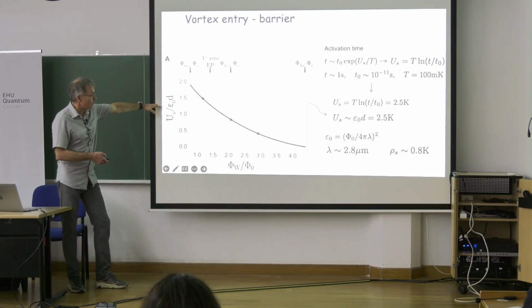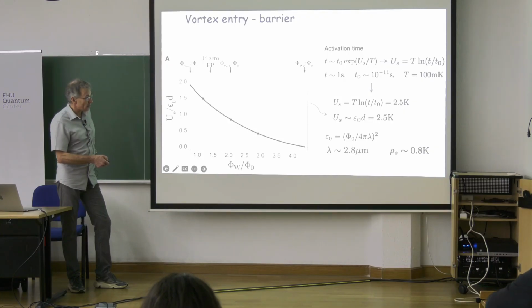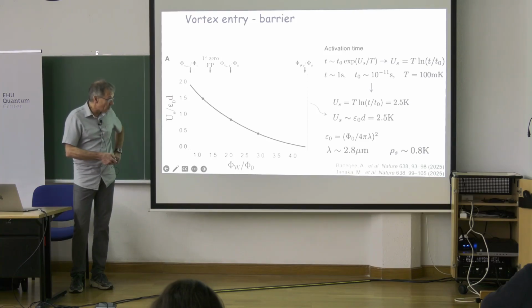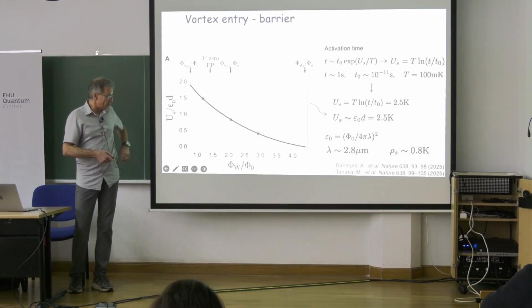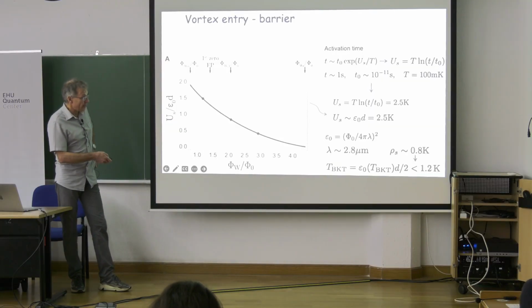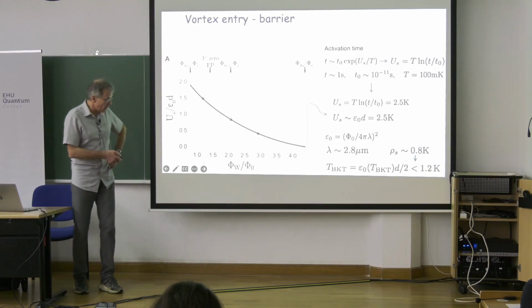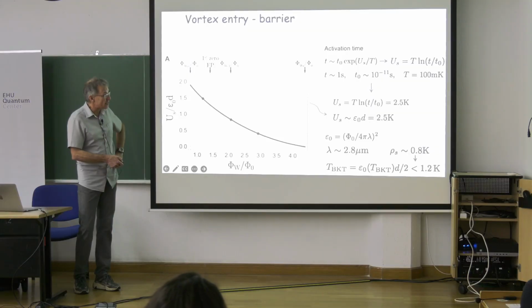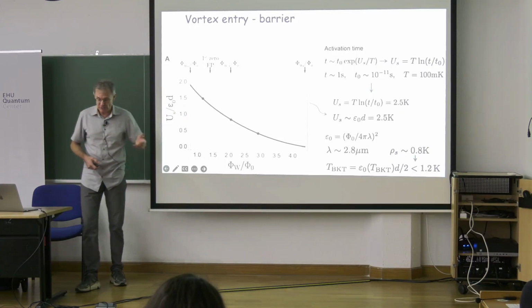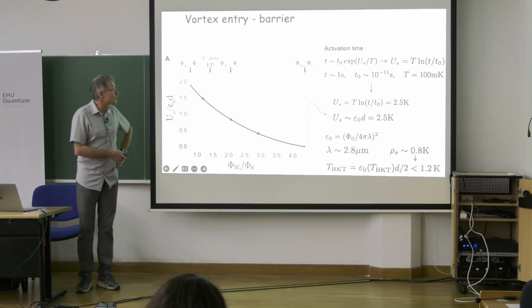From the other side, from this theory, this barrier is about the energy of a vortex in the film, which is the flux quantum divided by the London length squared. So equating this to this, we get a London penetration depth of about 3 microns and a superfluid density of about 1 Kelvin, which agrees well with the recent kinetic inductance study of two leading groups from Harvard and MIT. They study another bilayer and trilayer material, but they got a very similar value of superfluid density, which actually means that the temperature of the Berezinskii-Kosterlitz-Thouless transition would be about 1 Kelvin. And that's a temperature close to Tc, so this physics is of major importance here.